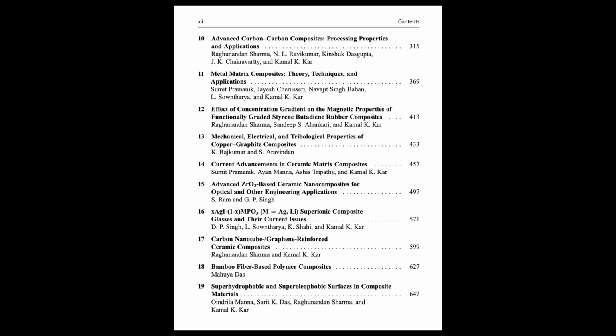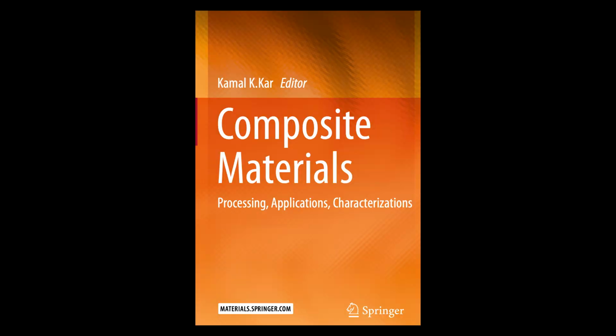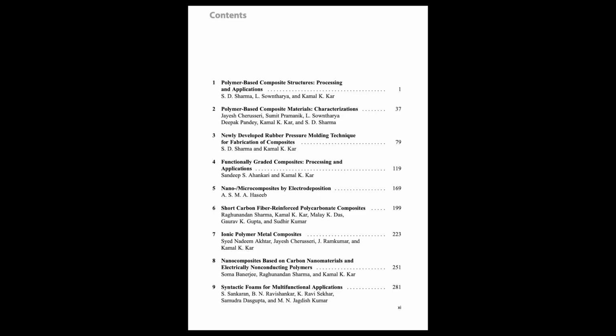Exactly. The rubber helps distribute the pressure evenly. Then you cure it maybe 16 hours at room temp, under about 0.65 MPa pressure in the example. And the rubber itself matters. Immensely. Table 3.2 showed different rubber formulations. The hardness, controlled by adding carbon black filler, affects how pressure is distributed and the final composite properties. Like what properties? Things like interlaminar shear strength, ILSS, how well layers stick together, and something they called crushed strength. Figures show these change with rubber hardness.